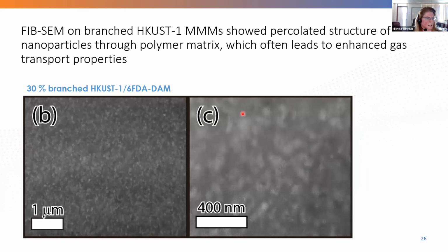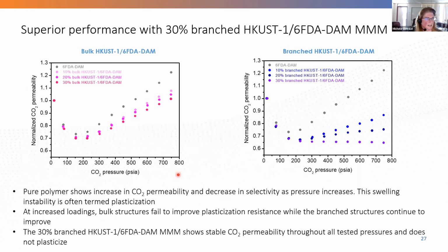Whereas when we look at the cross-section of our branched materials, you see a much more uniform structure that doesn't have these voids. You also have a highly percolated structure of these nanoparticles, which really enhances the gas transport properties. And so just some results on this use case, being able to compare the bulk versus the branched.